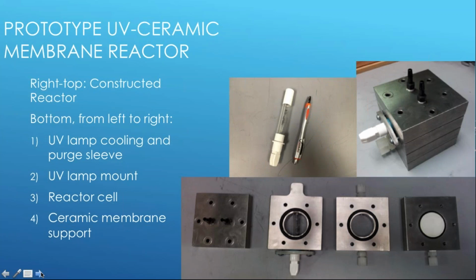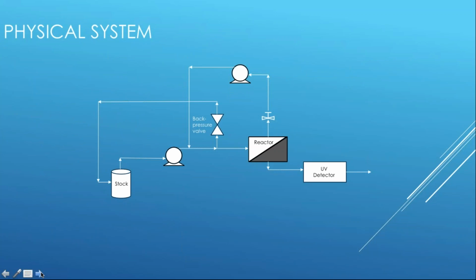Just to give you an idea of scale, the lamps were extremely small. During our initial tests, this is just a basic schematic of the system. We had a pump, and the pump fed the reactor, or fed into that membrane system. We also had a recirculation loop if we wanted to use it. However, for all the initial experiments, we didn't even utilize it. And then the effluent from the reactor went to a UV detector, and that's how we did most of our initial experiments, just using UV.